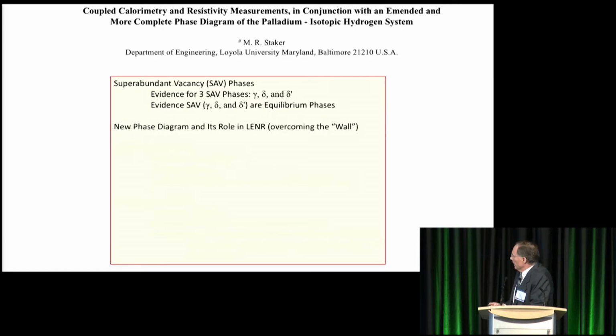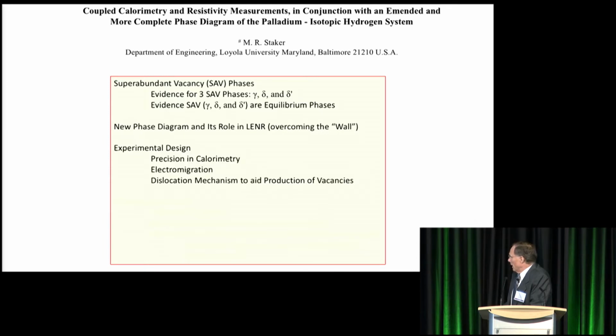One is the solid experimental evidence for the presence of these superabundant vacancy phases, gamma, delta, and delta prime, and also the other evidence that supports very solidly that they are, in fact, the equilibrium phases that will be on the phase diagram. I'm also going to have to skip the electromigration theory, and I will talk about the precision in the calorimetry, and I'm going to also have to skip the theory on the dislocation mechanism that produces large amounts of vacancies.